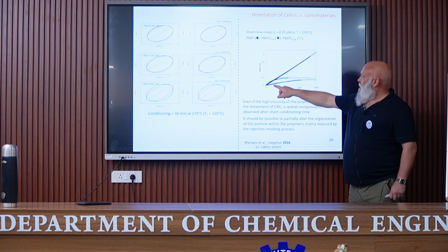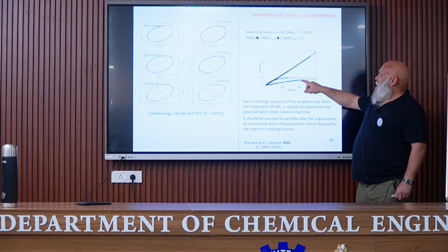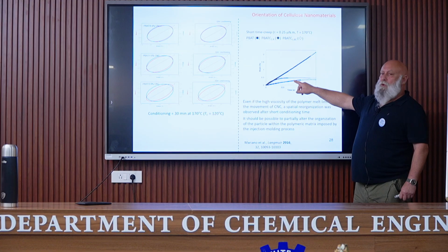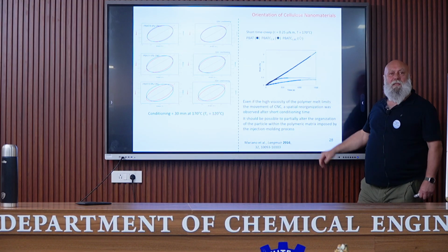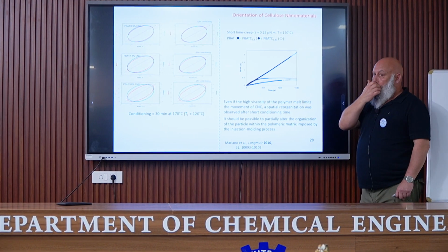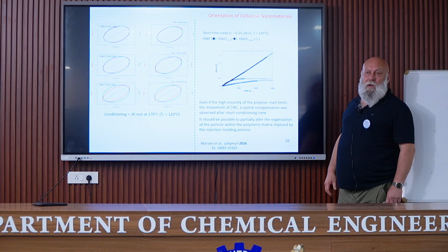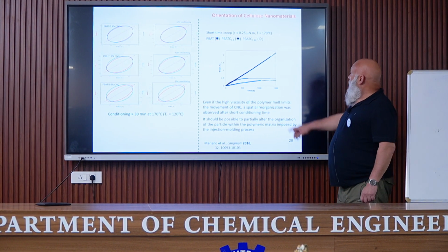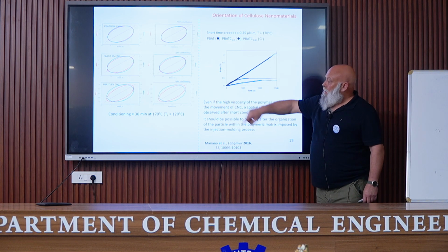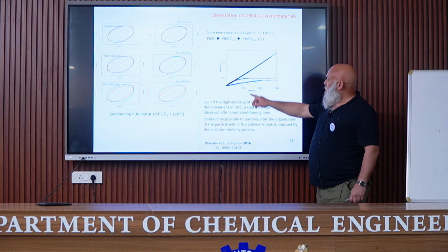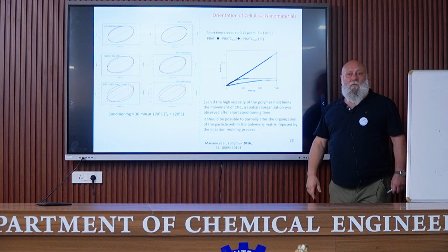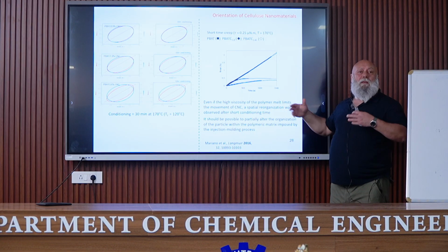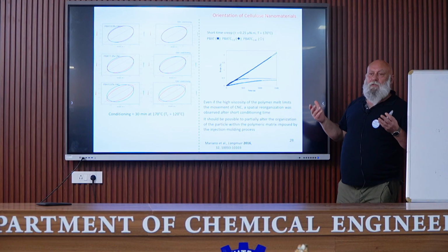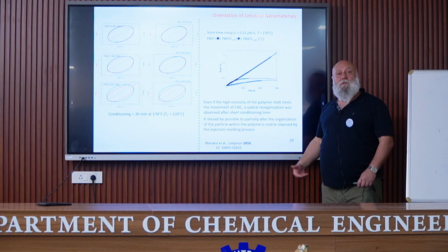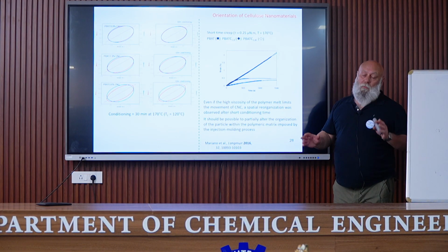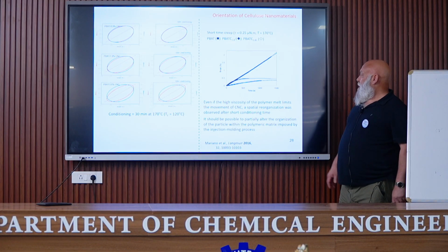Before conditioning, we have this behavior. You can see that we have an evolution and then a kind of stabilization. So this is typical of a solid viscoelastic behavior. And after conditioning at 130 degrees for 30 minutes, we still have a solid viscoelastic behavior, but it's different. Meaning that during this heat treatment, something happened. We don't know why, but something happened.